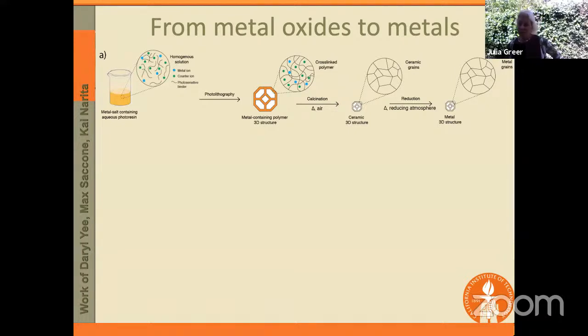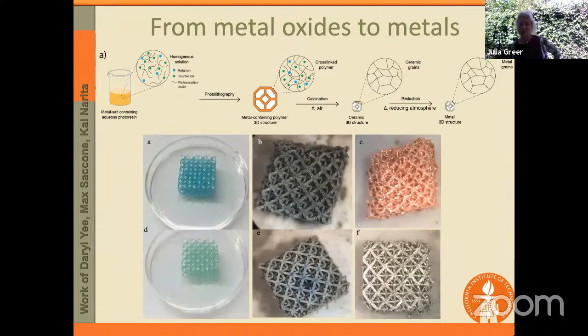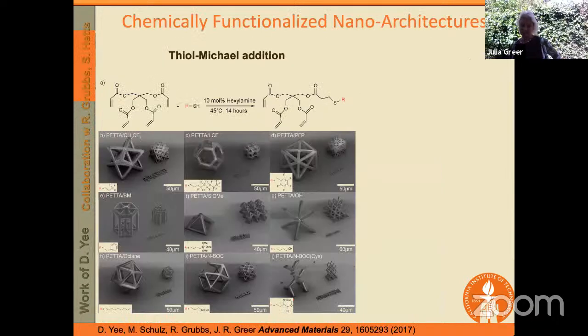Now, from metal oxides, the question was, well, if we made the metal oxides, can we further reduce them to their parent metal? And so what we're discovering is that, sure enough, you can see this is cuprous oxide and nickel oxide. And we first convert them into these black, of course, the black is representative of the nickel oxide and the copper oxide. And then once we reduce them, they turn back into their shiny color. And so this is a hydrogel-based way to create metals.